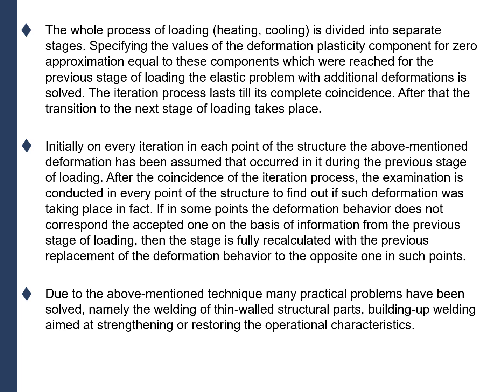If in some points the deformation behavior does not correspond to the accepted one on the basis of information from the previous stage of loading, then the stage is fully recalculated with the previous replacement of the deformation behavior to the opposite one in such points. Due to the above-mentioned technique many practical problems have been solved, namely the welding of thin-walled structural parts and building up welding aimed at strengthening or restoring the operational characteristics.